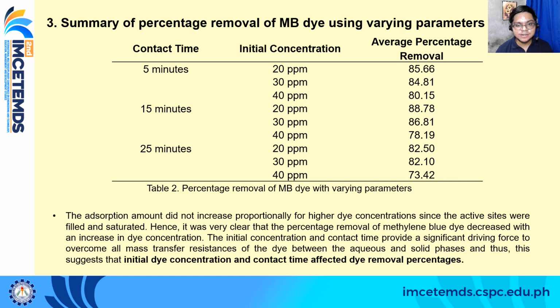From this, we can say that the adsorption amount did not increase proportionally for higher dye concentrations since the active sites were already filled and saturated. Thus, it is very clear that the percentage removal of methylene blue dye decreased with an increase of dye concentration. So we can say that the initial dye concentration and the contact time have a significant effect on the percentage removal of the methylene blue dye.